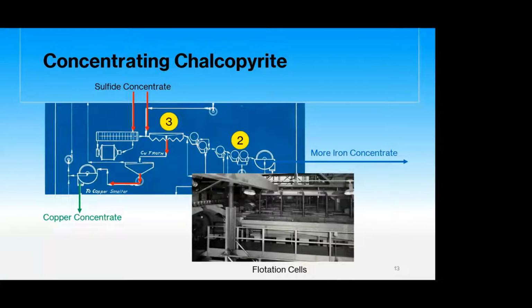At the end of the cycle in the flotation cells, which you see in the lower photo in this picture, the bubble froth containing the copper concentrate was then skimmed off the surface of the solution, further thickened, and then concentrated using filter processes. And these solids were the copper concentrate that was then sent off-site to smelters in Arizona, New York, Michigan, Canada, and Washington for further processing, including the extraction and concentration of the gold. The flotation plant also concentrated additional iron, like we saw before in step number 2, using the magnetic separators. This iron was then sent on to the sintering plant for final processing.